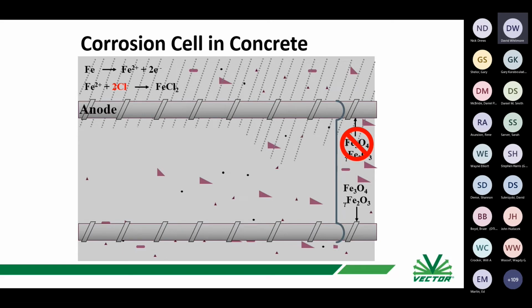And you're going to get a little bit confused because we're going to talk about using anodes to protect the steel from corroding. But any piece of metal that's corroding, that's giving off electrons, is by definition an anode. So an anode is an electrode that's giving off electrons. And the corroding steel at this location where you have chloride contamination is an anode.